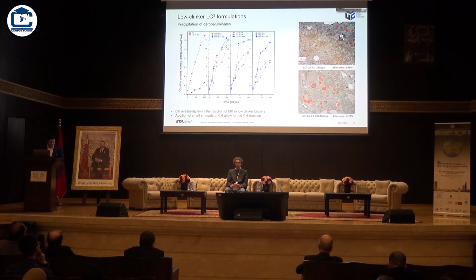In terms of microstructure, this basically means that we have all of this hemicarbonate and monocarbonate, which we know now precipitates occupying large pores left behind by clinker hydration, reducing porosity very effectively, very quickly. This is a reaction that has its peak between 2 and 3 days of hydration, and definitely contributes to this gap difference between a system with 25% clinker and a system with 65% clinker, depending on the SCM that we're using.